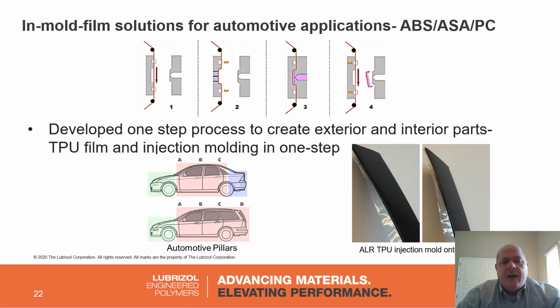And finally, another application that kind of came as part of this as a spin-off, it's somewhat separate. It's an in-mold film solution for different molded parts using ABS or ASA or PC or PC ABS or any plastic that TPU will readily stick to. I'm going to walk you through the top piece here, 1 through 4, on what's happening in the diagram on the top. And the first one, you can see that film would roll in front of the mold, just in the mold on the top.